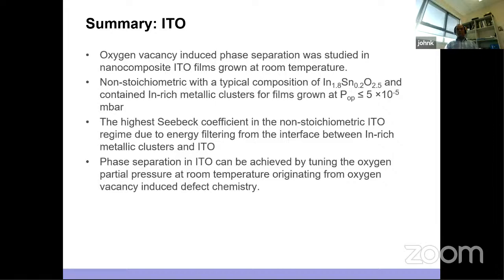There is a non-stoichiometric nature depending on the operating pressure you put in the chamber, and it is also related to indium rich metallic clusters. The highest Seebeck coefficient is actually in the non-stoichiometric ITO film, which is explained by energy filtering, where the interface between the indium rich metallic clusters and the ITO contributes to the energy filtering effect. It's really cool to see that we can tune these kinds of effects.